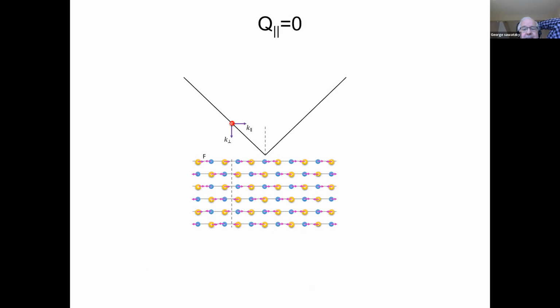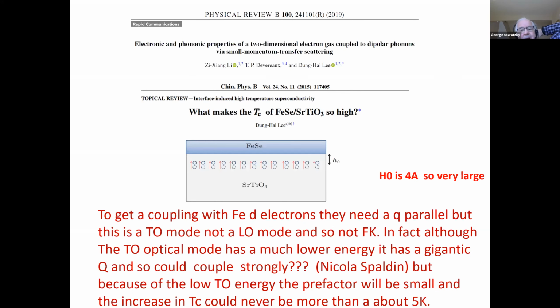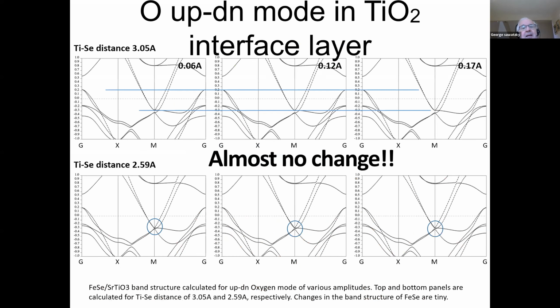However, in TC, that phonon frequency is the prefactor. And so I can't imagine that it could give you anything more than perhaps a 5 degree Kelvin change. We actually did what I call a poor man's electron-phonon coupling calculation, just to see what happens if we move the oxygen atoms in this polar mode in the strontium titanate and look at what happens to the iron selenide band structure. And remember, the iron is about 4 angstroms away from the surface of STO.